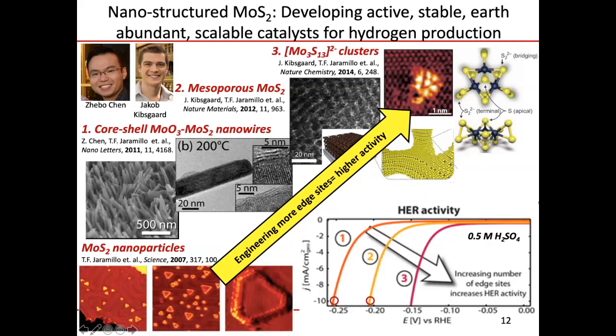And so here's a polarization curve to show you some data. This is in sulfuric acid. The equilibrium potential for the reaction is, of course, at 0 volts versus the reversible hydrogen electrode. And what you want is as much current as you can possibly get, as close to the equilibrium potential as you can. You can see from formulations 1 to 2 to 3, going from nanowires to mesoporous materials to these small molecular clusters, we're able to march along and operate closer and closer to equilibrium.